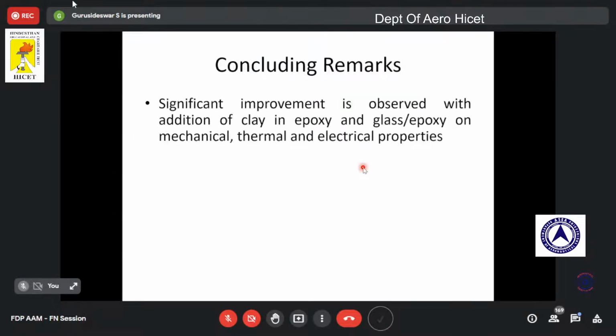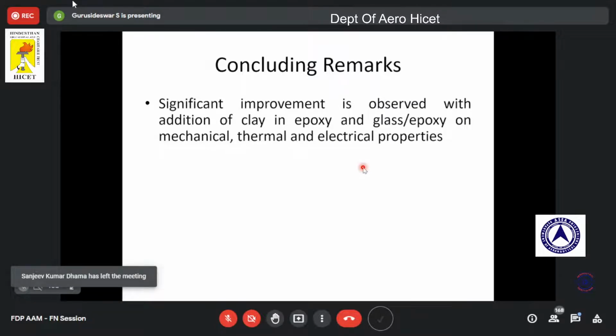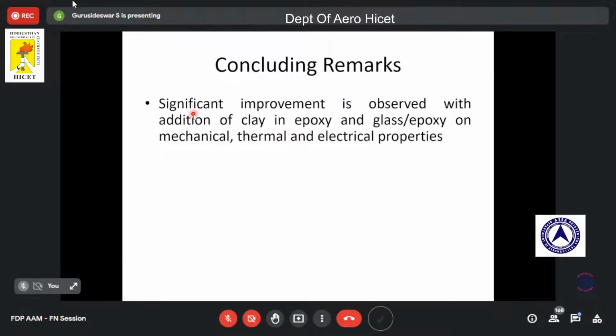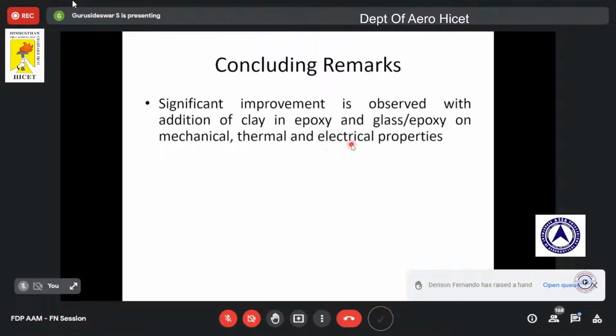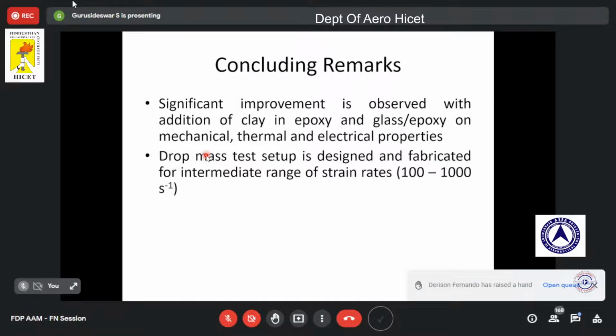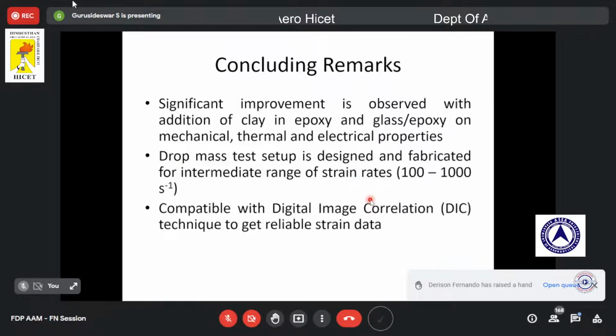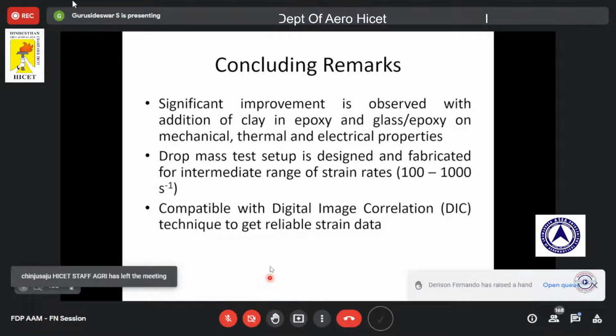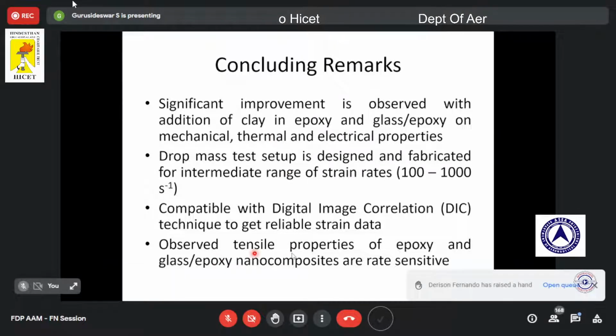Yeah, so these are my concluding remarks. We have observed that addition of clay in epoxy polymer and the composite leads to good improvement in mechanical, thermal, and electrical properties. We have successfully employed the drop mass setup to achieve intermediate strain rates. And we have found that DIC is highly compatible with the drop mass setup to get reliable strain data. Also, we have found that the tensile properties of both epoxy and glass epoxy composites are rate sensitive.